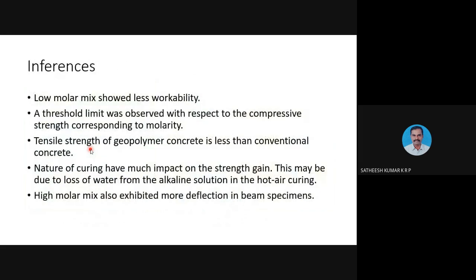And some of the inferences from this study are, the low molar mix. They showed less workability. Like for the slump test, we were able to get only 5 slump for the first two low molar mixes, namely the 6 molar solutions and 8 molar solutions. Whereas the workability was relatively high. We were able to get around 20 slump for the other mixes. The slump value is also very low because we used more amount of coarse aggregates.